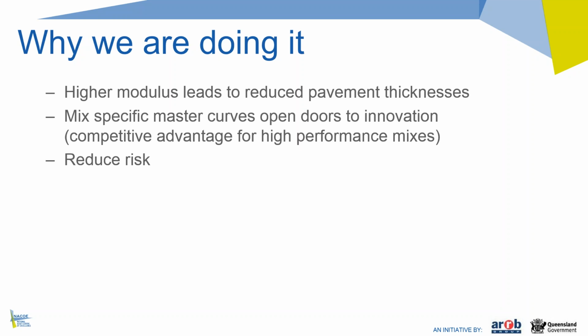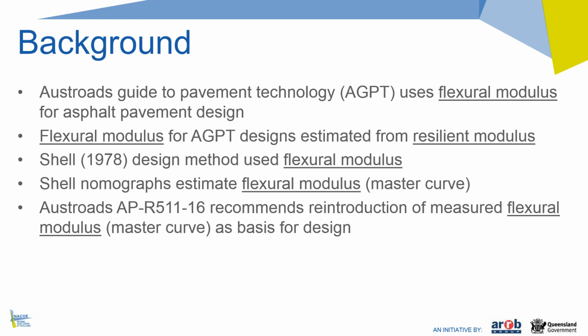Well, first of all, the basis for the modulus in the Austroads design guide has always been the flexural modulus. The flexural modulus in the Austroads guide is estimated from a resilient modulus value. And the reason why Austroads uses flexural modulus is because it's based on the Shell design method from 1978, which also used the flexural modulus.